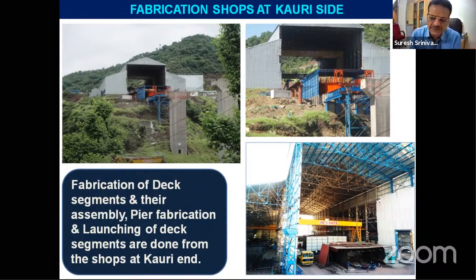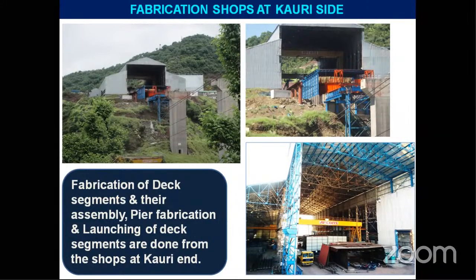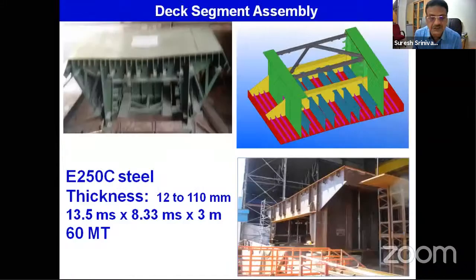Besides the standard test weldments, which are used for establishment of WPS and PQR, we also proceeded with a mock-up fabrication. Mock-up in the sense, the cross-section is the same, the width is the same, only the length is minimized. This was done to prove that all our procedures and PQRs were established in the real structure. Then only we moved to the actual fabrication. All our assembly and welding sequence studies were initially tried out on this mock-up structure, tested completely by NDT. Then we proceeded to the actual job.